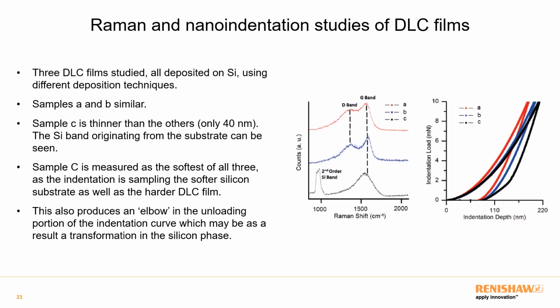For this example, I've got 3 DLC films. They're all deposited on silicon, and they were nano-indented. The central figure shows the Raman spectra for each of these films. They have D and G bands, standard for DLC type films. You can see that A in red and B in blue are quite similar. Film C in black is a little bit different. There are 2 key differences. One, you can see the presence of the silicon second order band, and that's because the film itself is very thin, only 40 nanometers. The other thing to note is it doesn't have a very strong D band, and that will affect its mechanical properties.